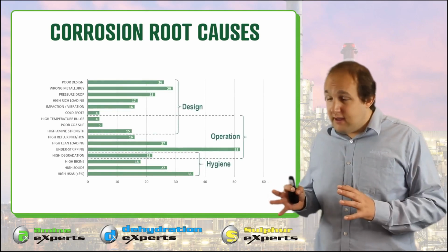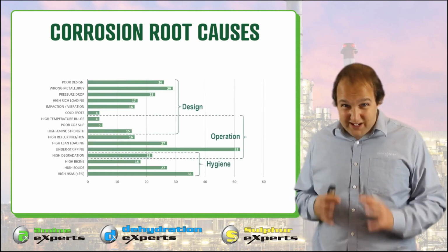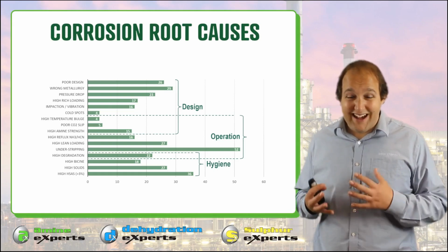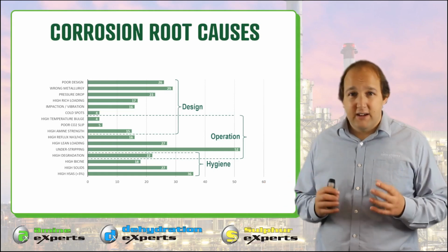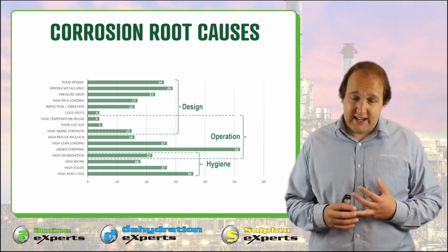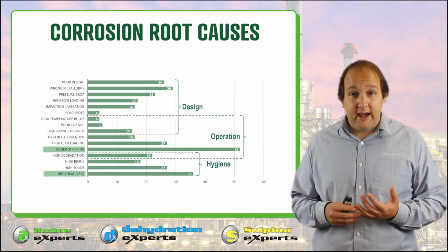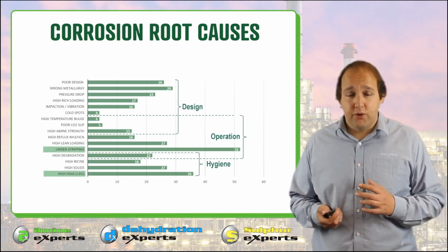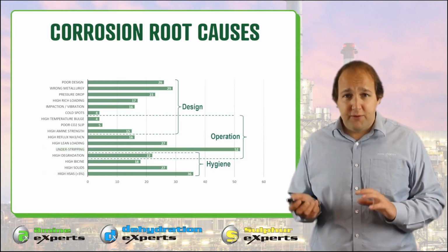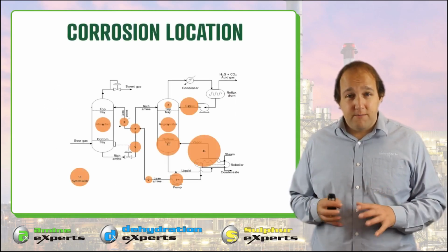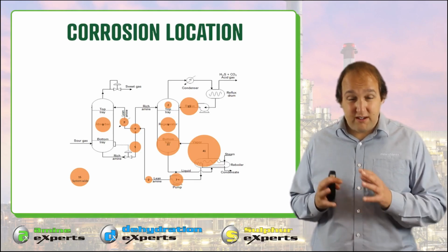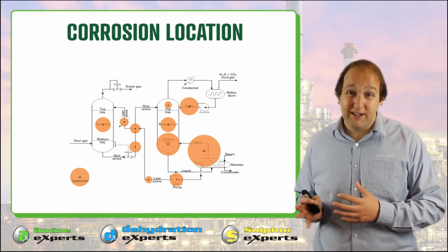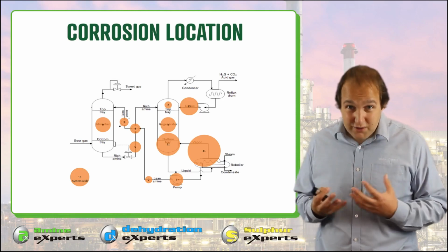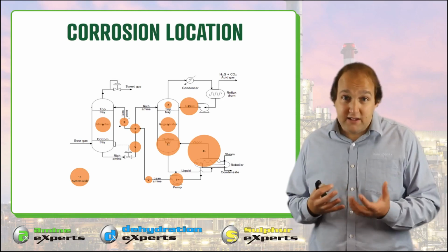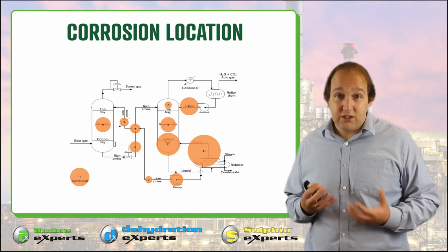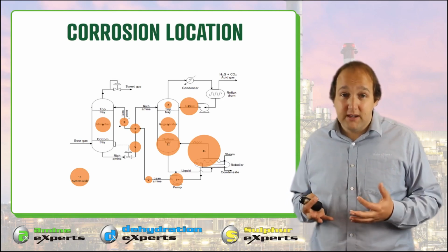So broadly speaking, we can divide corrosive failures up into three different categories: design, operation, and hygiene. And when we look at this trend, what we see is that two root causes really stand out, and that's understripping and high heat stable salts. So I'm going to dig into those, but first we're going to take a look at where corrosion occurs. So the bulk of the corrosion in the amine system occurs in the hot section, so the bottom of the regenerator column and the reboiler, which accounts for almost half of the 131 corrosive failures that we've seen. And this makes sense because corrosion is a chemical reaction and the kinetics of it increase with temperature. So the higher temperature parts of the plant are going to corrode faster.